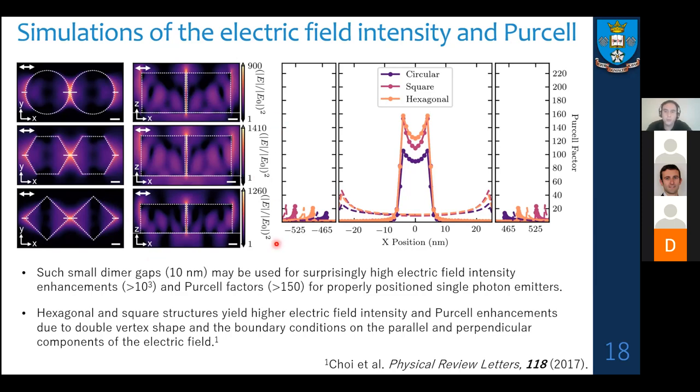And if we were to simulate a dipole positioned at the top surface of these nano antennas, the Purcell factors it would experience would be higher than 150, almost 160. So bringing these together is very important in order to reach these high Purcell factors in Mie resonators.